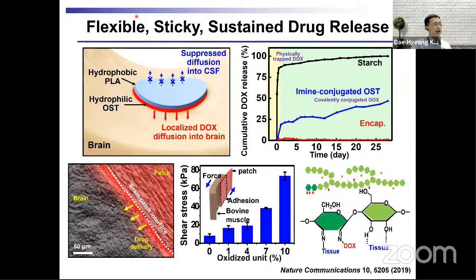Also, the cavity is filled with CSF, cerebrospinal fluid, and without the encapsulation layer, the loaded drug will be released to CSF. Then we will waste the valuable loaded drug. So we passivate the surface with a hydrophobic PLA layer to prevent unwanted drug leakage to CSF. So after encapsulation, we could suppress the drug release significantly.